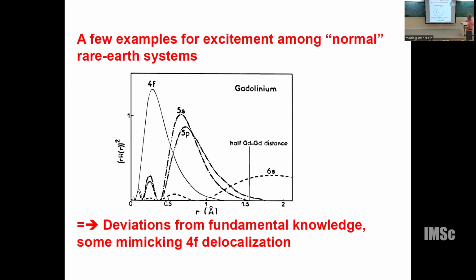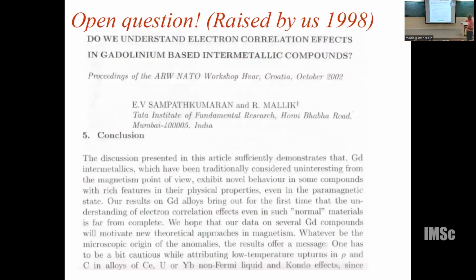Now I will point out one excitement when it comes to heavy rare earths, which made a difference to the field. As I already mentioned, for gadolinium, the radial extension of the 4f orbital is deeply localized. One may expect that it's a dead vegetable, nothing interesting, and it was going to be so for decades till recently. And we found some anomalies in this compound which mimic some cerium compounds.